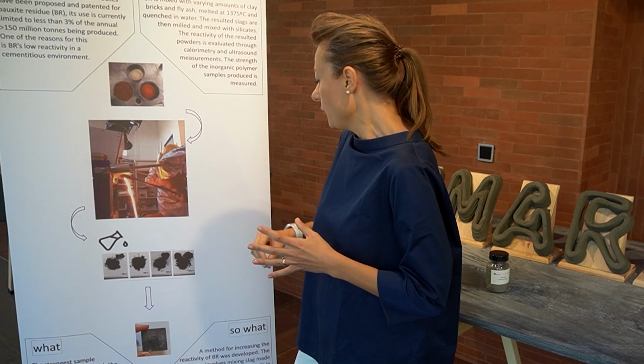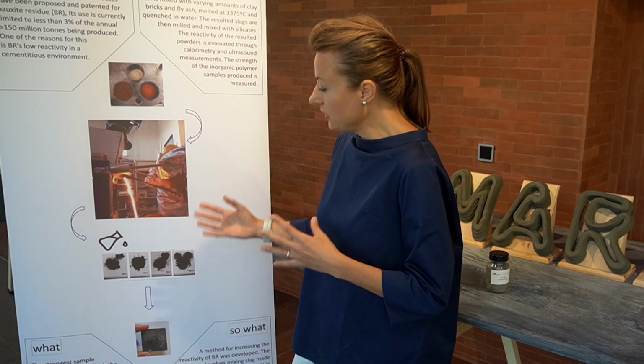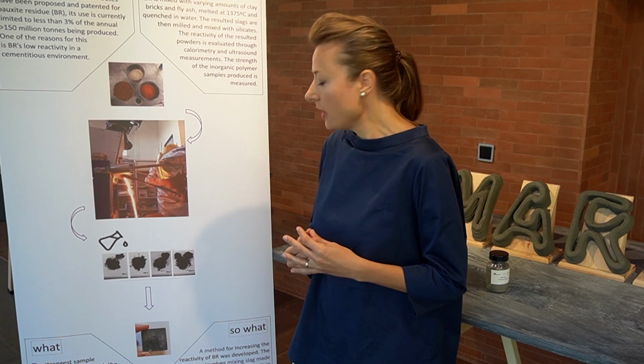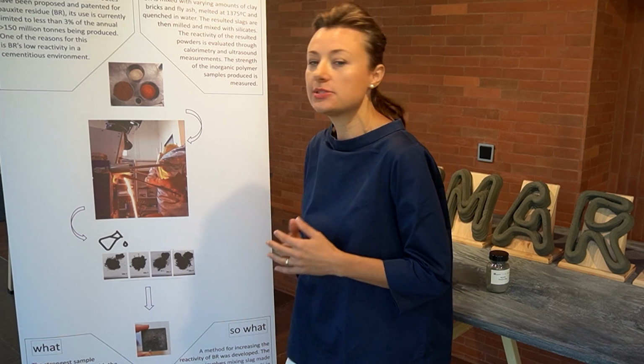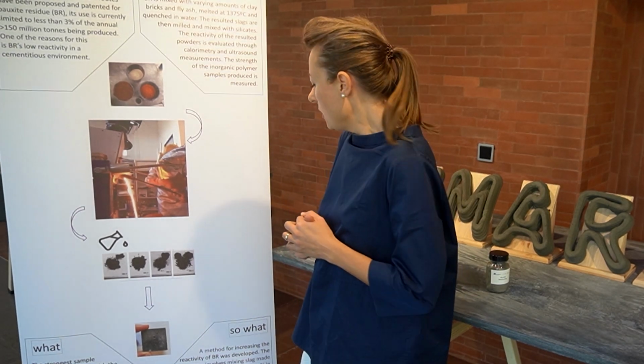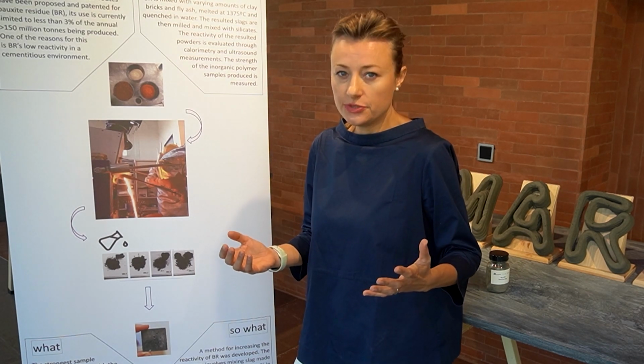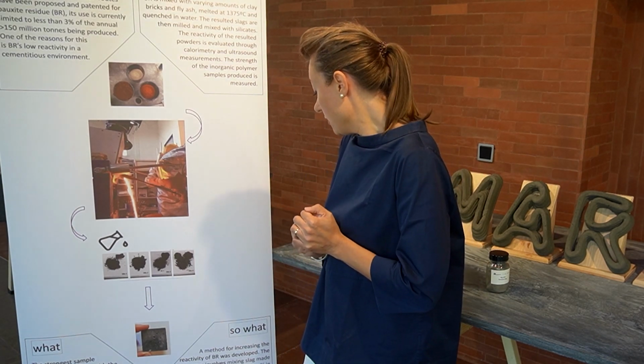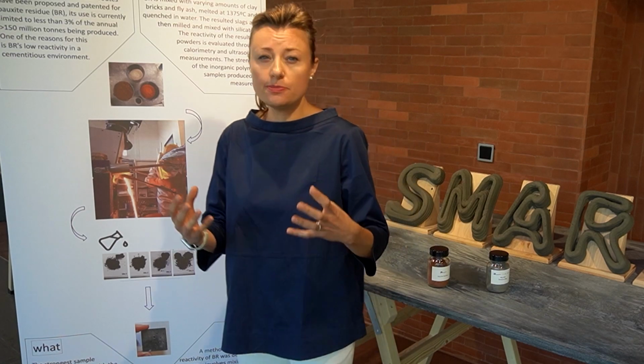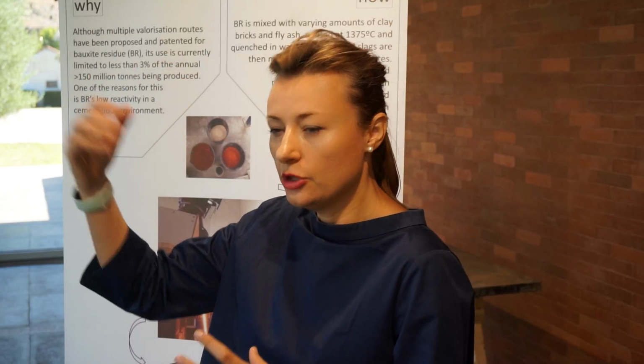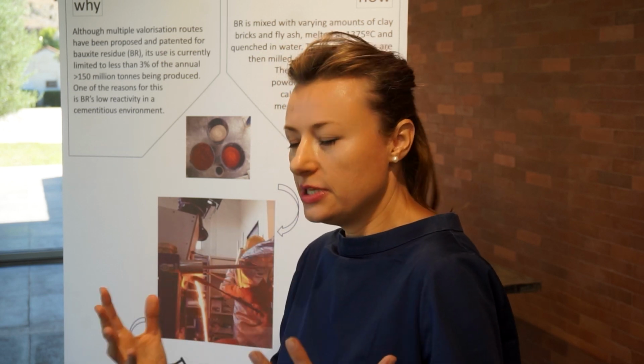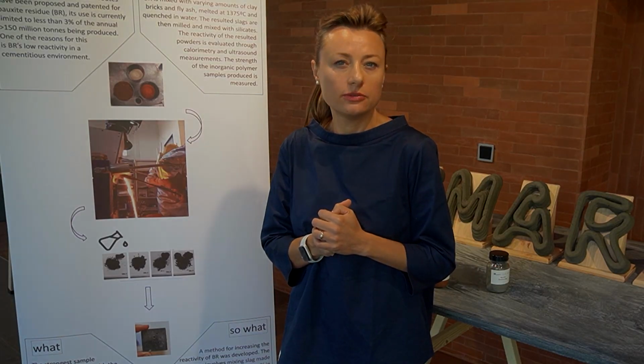After we test them and we've seen which slag is better, we also made samples, and the best sample we had is almost 100 megapascals after 3 months. This of course is a very good compressive strength, so then we decided that we would use this material at a higher scale to do bigger samples. So more or less this is what we've done in the work package.